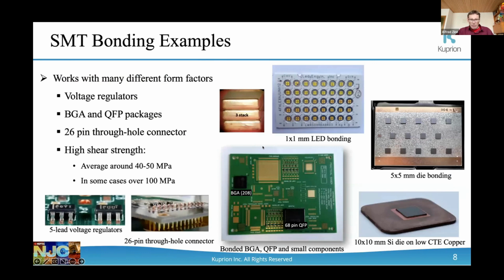So here's some different flavors of what you can do with the material. It is very easily dispensable. You can make stacked systems. You can do actual full 3D integration, because you can do multiple layers. Once the material is fused, it reverts back to bulk copper. And that means you can heat it as many times as you want. So you can do 10 layers or 10 different reflow cycles. The previous ones, they don't do anything. They just sit there happily. If anything, they'll continue to sinter and become stronger and better.